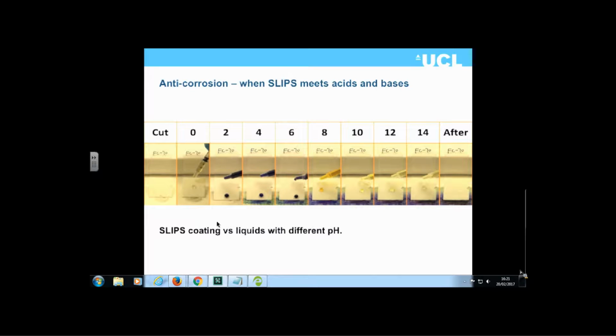The surfaces are also very corrosion resistant to both acids and bases, and we've done tests where we've had a metal base coat which we then overcoated with our SLIPS surfaces, exposed them to both acids and bases and show no degradation of the underlying material.